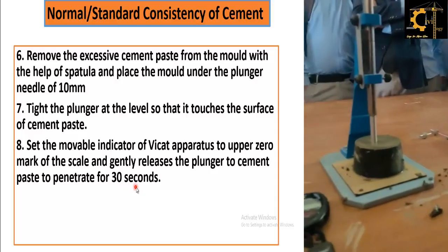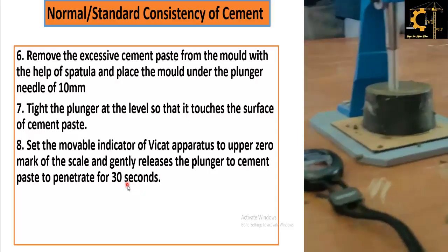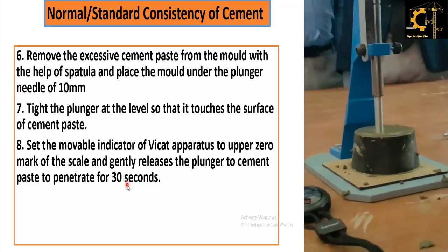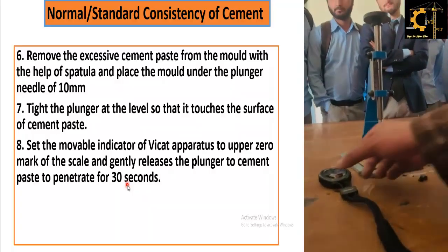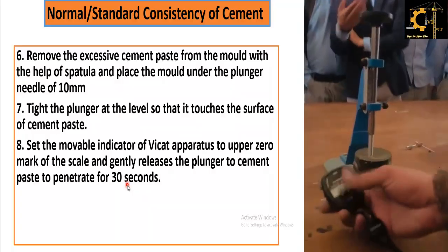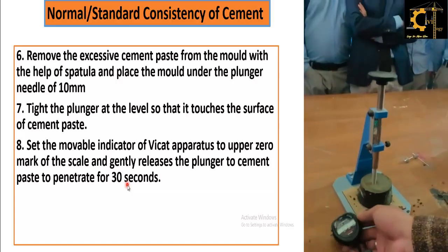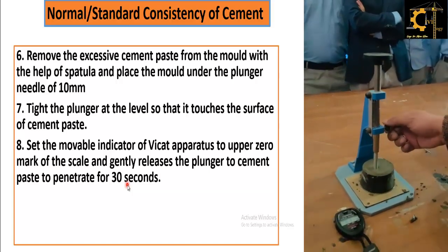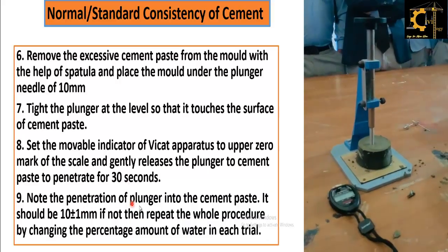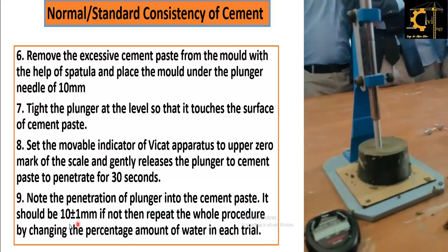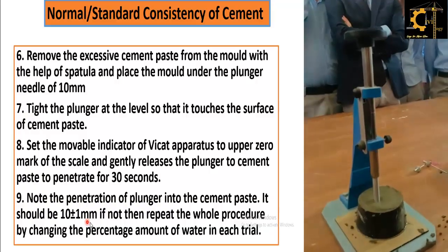Now this is the gauging time. This is very important to note because we are following the ASTM standard, and it says that in 30 seconds the plunger has to penetrate 9 to 11 millimeters. So a stopwatch is necessary over here. Note the penetration of the plunger into the cement paste. It should be 10 plus minus 1 millimeter.